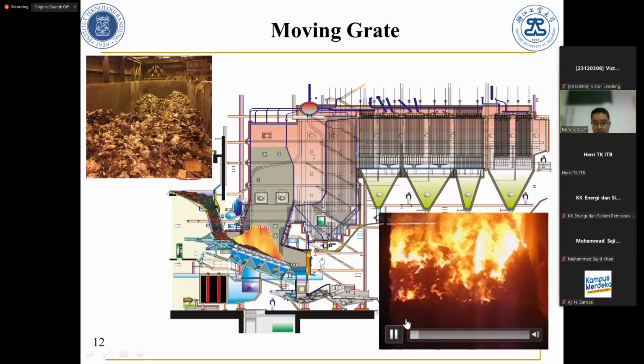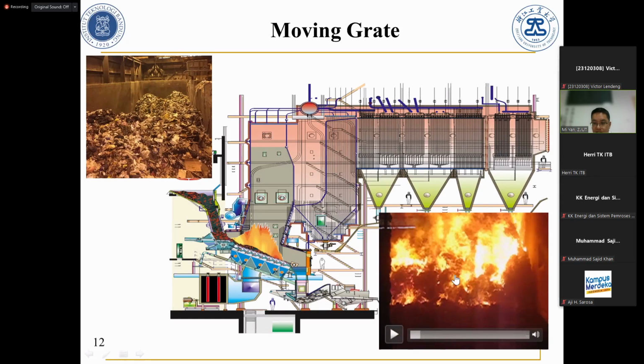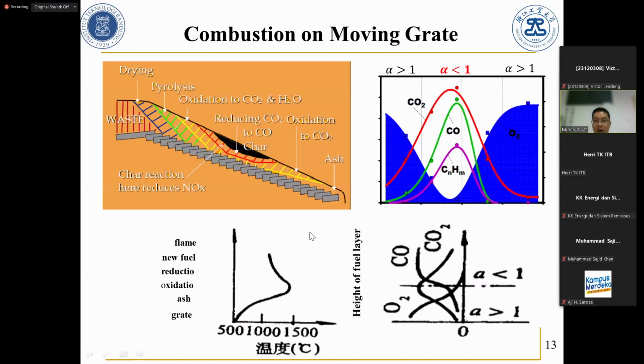So this is the inside of the grate. You can see the fire is very strong, right? And this is the waste in the tipping hall. The MSW is decomposed on the bed of the grate. So we can simulate what happens on the grate. The waste is fed from the left, then it goes through drying, pyrolysis, gasification, or combustion. And here CO2 is reduced to CO, or char is produced, and at the end it produces ash, or we call it slag.